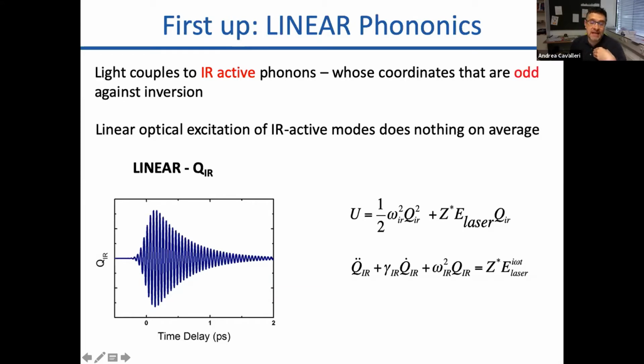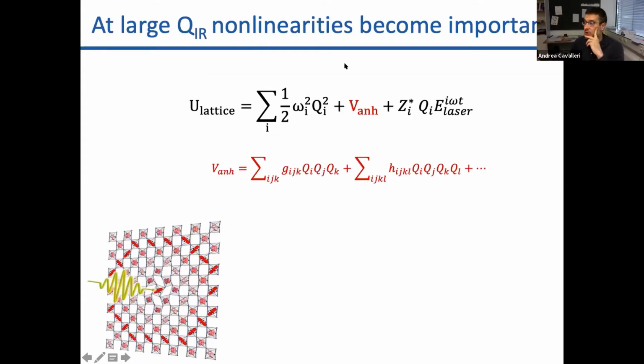So if I can now generate light fields that are strong enough, obviously this type of treatment will not be sufficient anymore. So two things are going to happen. If I now have a large electric field and therefore large displacements of a driven mode, firstly, the normal mode that I was describing before, which I called Q_IR, is no longer the only mode that responds in the solid. So I should consider the potential energy contributions of all the phonon modes. Plus, there's going to be an anharmonic term, which I will tell you about in a second, plus the same laser interaction term in the energy that I was discussing before.